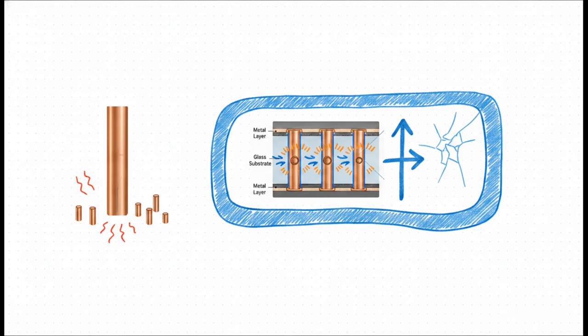That little blue layer surrounding the copper is a vital polymer layer made of materials like ABF, epoxy, or polyamide. When the solid copper inevitably heats up and expands, that soft polymer layer acts as a thermal shock absorber. It takes the absolute brunt of the expansion and completely saves the fragile glass from cracking.